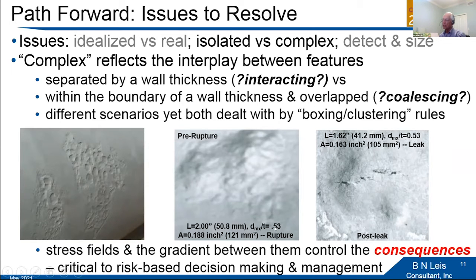Notice here that the maximum depth, in this case, this one, is 0.53. The same is the case for this pair. In this particular case, this is a slightly shorter feature as compared to this one. This is a view pre-rupture. As you can see here, leak paths have formed, and this is a post-leak image. This combination leaked because the barrier between these two features was relatively shallow and they could coalesce. As they coalesce, they fail at a lower failure pressure. But because these two features are relatively resistant to failure, they don't coalesce and they gave rise to rupture. So the significant difference here is a leak, which is a relatively small release through these very, very tiny cracks. Remember, this feature is just a little less than 2 inches long. So this is a critical element of the problem.